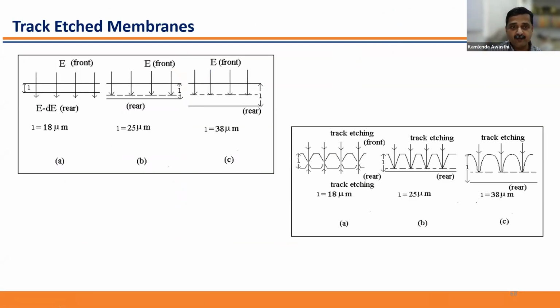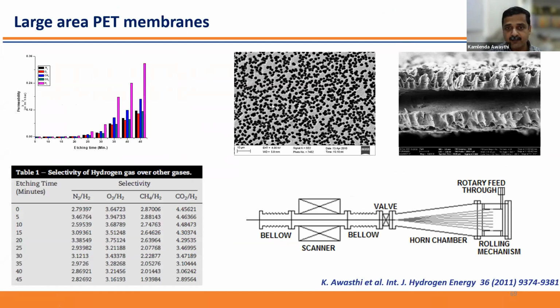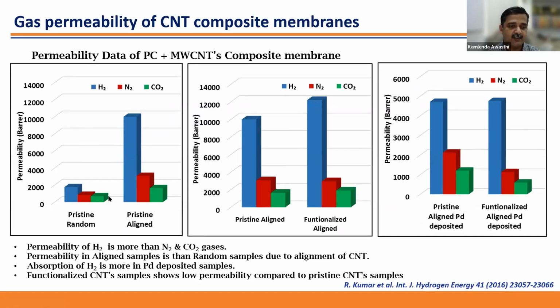In the case of track-etched membranes, we have a nice pore size distribution over the surface. Here you can see that as we increase the etching time, removing more material, the permeability increases and goes very high. This is particularly for hydrogen, but at the same time, once we have sufficient porosity in the sample, the selectivity is not good. So what can we do? Another thing we can do is make a composite. Here we tried random and aligned CNTs, and you can see aligned CNTs are better than the pristine one. Then we tried depositing some palladium nanoparticles, and these membranes are better than the others.